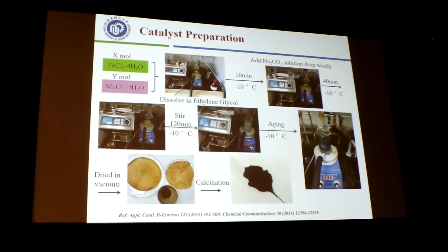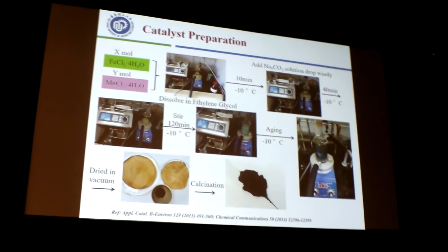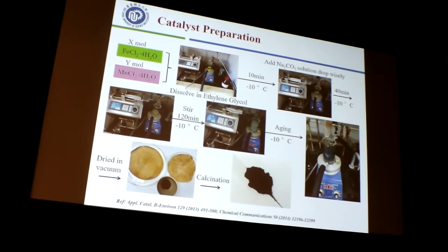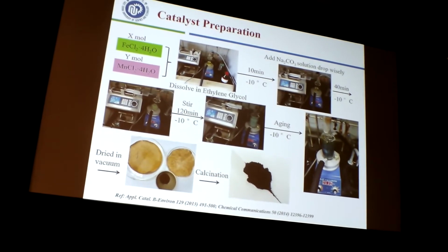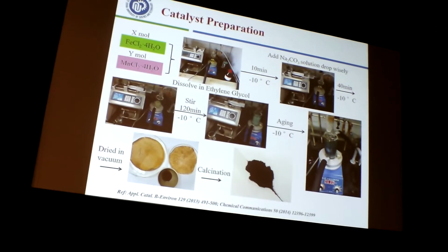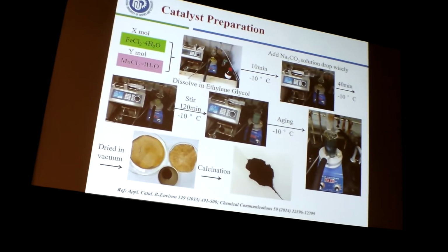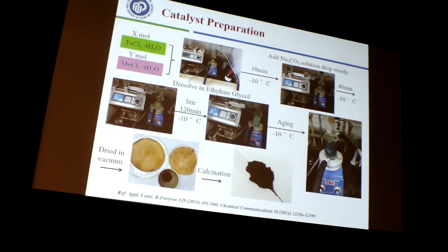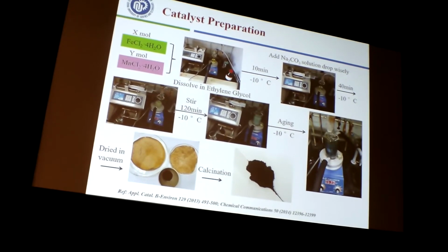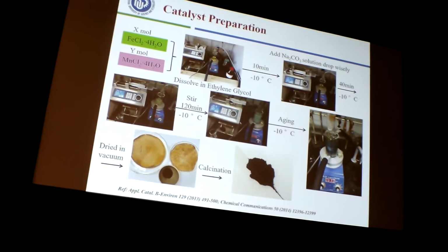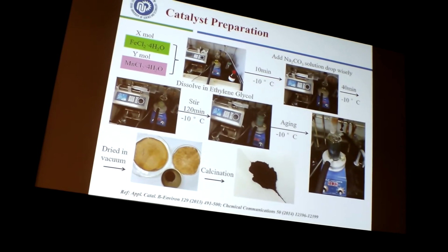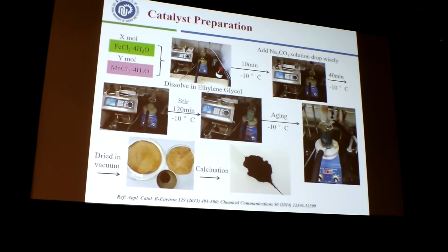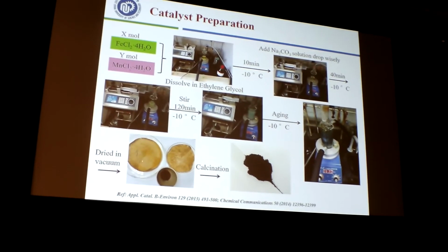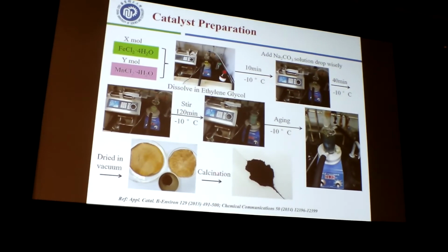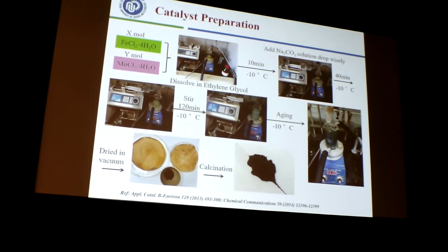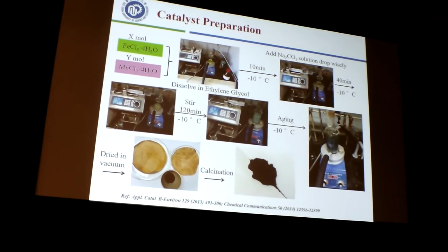So in our study, we prepared our bimetallic catalyst using a low temperature co-precipitation method. What happens is that the metal precursor is first dissolved in ethylene glycol, and then undergoes the low temperature co-precipitation. After aging for several hours, washing and drying in vacuum, we calcine our catalyst precursor to obtain the catalyst.